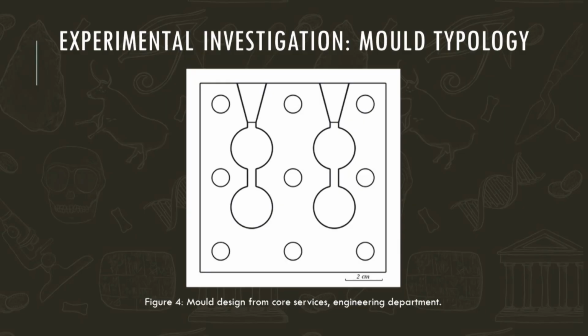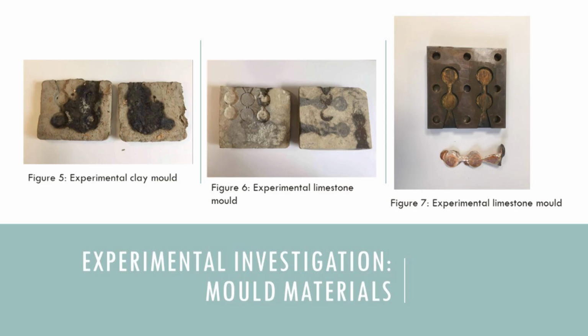The evidence from the visual inspection suggested that ancient silver copper flans were produced in moulds with connecting channels, and the indentations are connected by channels which allow molten metal to flow throughout the mould. When designing the mould, I looked at the average diameter for the coins investigated, which was around 20 millimetres, and the thickness was 1 millimetre. So to produce blanks of a similar size, standard indentations of 20 millimetres diameter and 3 millimetre depth were made. The depths of the indentations were made larger to account for both shrinkage in the mould and the reduction in size caused by striking.